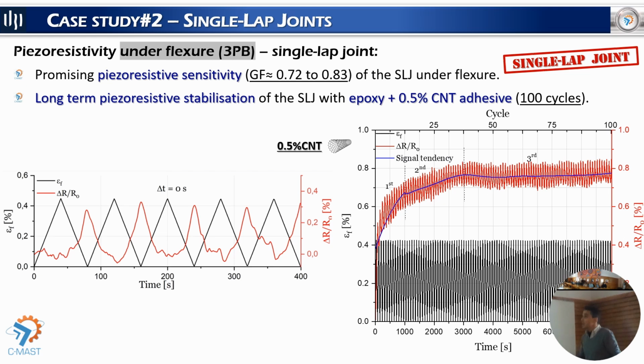Then we applied this adhesive to glue adherends to build the single lap joint, and we tested again the piezoresistivity of the structure in cyclical 3-point bending tests in flexural mode, of course. And here we verify again that when the stress is applied and removed, the electrical resistance varies again. But here the variation is the opposite of the first case. Here we have a negative piezoresistivity. What does this mean? In the first case, when we applied stress, the electrical resistance increased. Here, when we applied stress, the electrical resistance decreased.